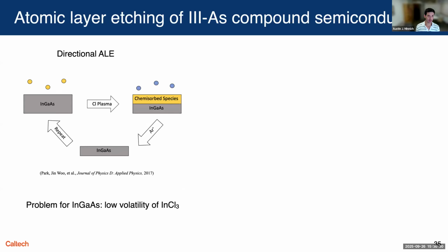So for example, some of the earliest ALE processes for 3-5 semiconductors consisted of exposing InGaAs to a chlorine plasma that would create chlorides on the surface, which you could then sputter off with a low energy argon beam. And that energy was chosen low enough that it wouldn't hurt the InGaAs too much, but it would remove the modified layer. And this is now actually done for nitrides. The problem for InGaAs is that you form compounds like indium chlorides, which are not very volatile, requiring a kind of energetic argon step to remove. And that creates traps.